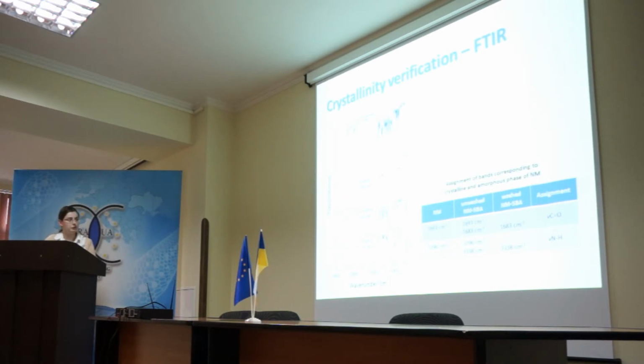Another confirmation of amorphicity of our drug after loading and washing is infrared spectroscopy. Here, the main changes may be observed in two regions, about 2,300 and about 1,070 reciprocal centimeters. Here, in the unwashed sample, we can see